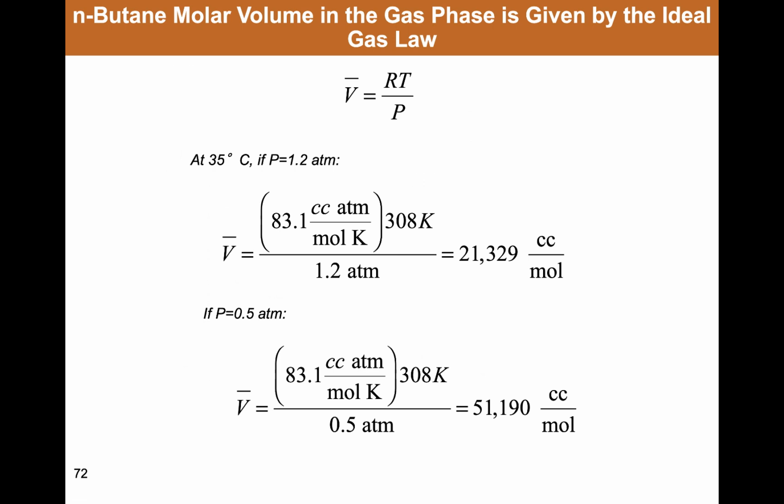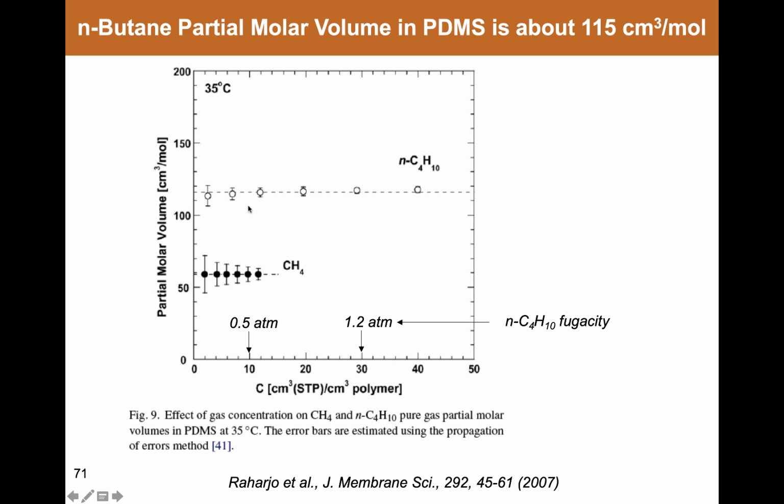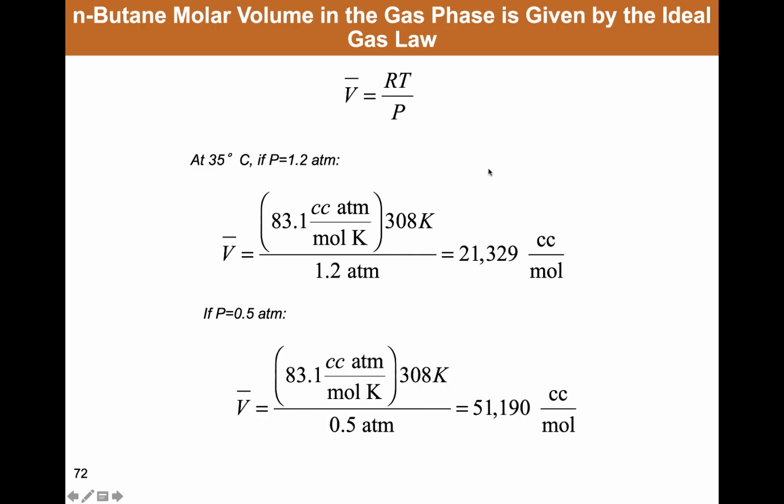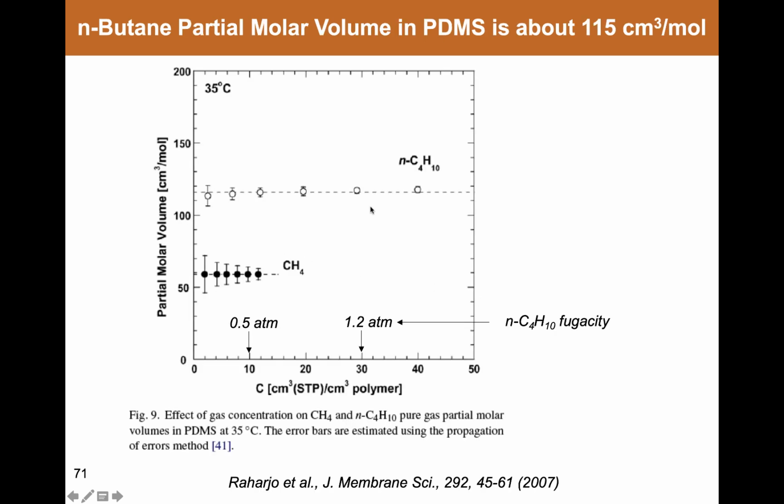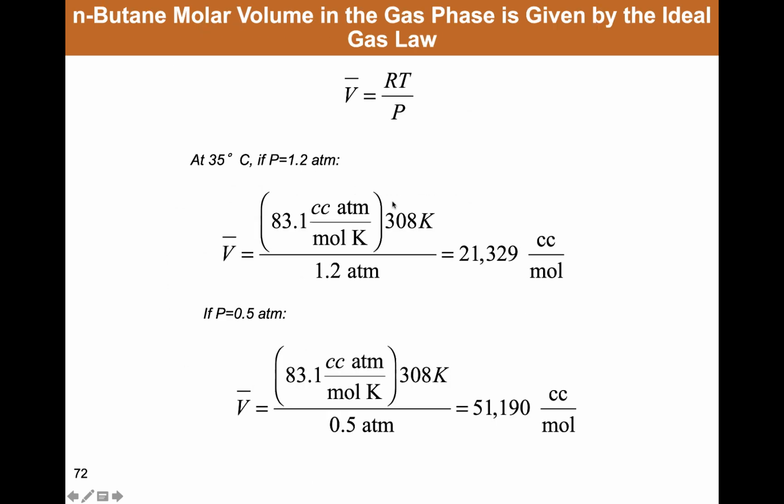So unlike the liquid case, where the molar volume of the liquids was about equal to the partial molar volume, in this case the molar volume of the gas is enormously larger, orders of magnitude larger than the partial molar volume of the gas dissolved in the polymer.